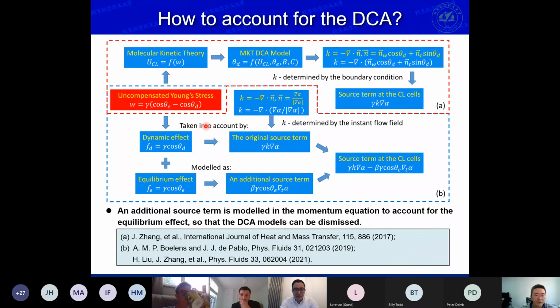But now we found that we can use it in an alternative way, because we can decompose the uncompensated Young's force into two parts, the dynamic effect and the equilibrium effect. The dynamic effect has been implemented in the VOF method automatically, and we only need to supplement an additional source term into the momentum equation. In this way, we can dismiss the dynamic contact angle. We can capture the curvature of the interface automatically.